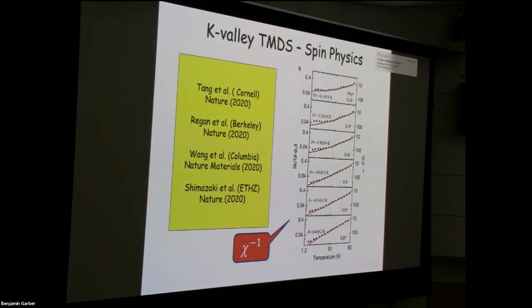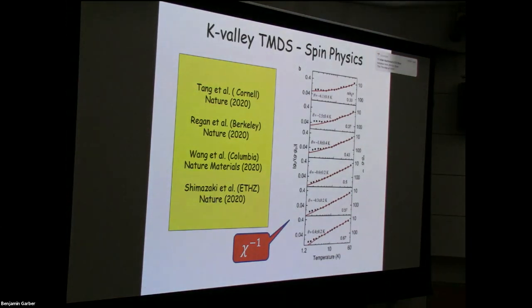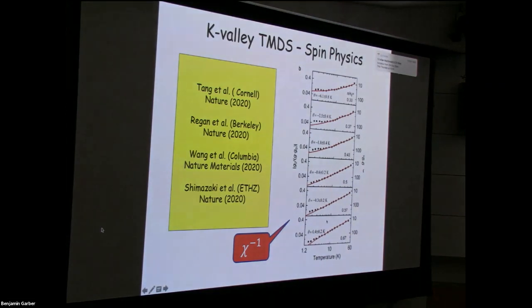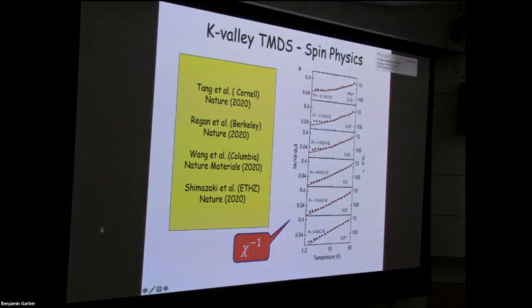So that idea has now been successfully explored by many experimental groups. I think these papers from 2020 are the first experiments. The figure on the right shows a measurement of the spin polarization versus magnetic field in these artificial crystals. The spin polarization is measured optically. I won't describe exactly how it's done, but a lot of the way these are explored is based on understanding that had been developed by Professor Heinz and his group over the years, and many other groups, a very detailed understanding of optical properties of these systems. And this is basically some sort of magnetic circular dichroism.